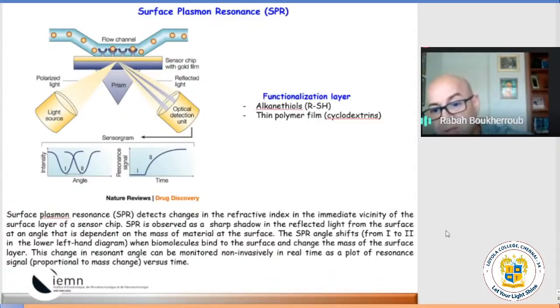You have a laser here, it's a general red laser, 670 nanometers. And you have here a glass slide with a very thin gold film. Well, of course, you have the adhesion layer of titanium in between, which is below 5 nanometers. And the gold layer is about 45 nanometers. And what's happening actually when you choose, normally light is reflected from the middle, but at this interface, if you are at the right angle, you have what you call a minimum reflection. And this minimum of reflection will keep the same angle.